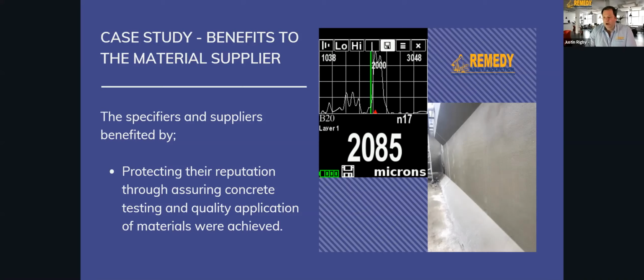The image here on the bottom right corner is the final image of that tank, where cementitious polymer, the waterproofing, has been applied over the top. So you can see that the tank is in much better condition than what it was to begin with. And the graph there is an ultrasonic image of how we can measure the thickness of the waterproofing. So we're able to measure the waterproofing over the top of the mortar. In this example, it's 2,085 microns thick, which is basically 2 millimeters of thickness. Using that technique, wherever we find low spots, we can have those areas reapplied and have extra thickness applied.